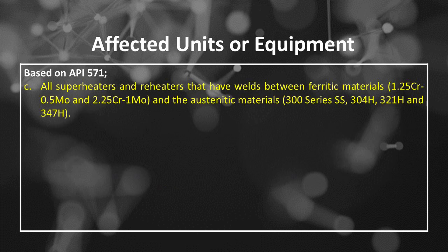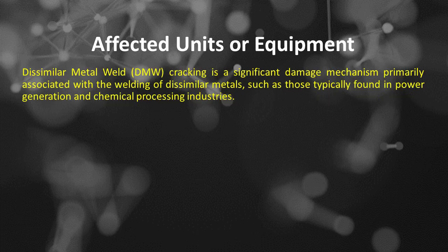The third is all superheaters and reheaters that have welds between ferritic materials, 1.25Cr-0.5Mo and 2.25Cr-1Mo, and the austenitic materials, 300 series SS, 304H, 321H and 347H. Dissimilar metal weld, DMW, cracking is a significant damage mechanism primarily associated with the welding of dissimilar metals, such as those typically found in power generation and chemical processing industries.